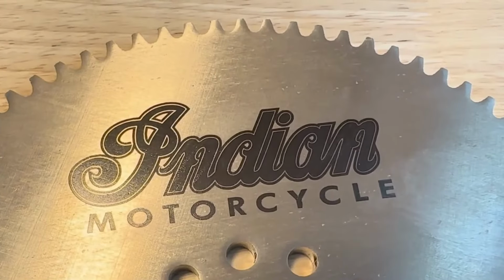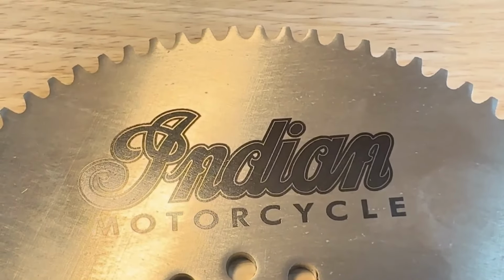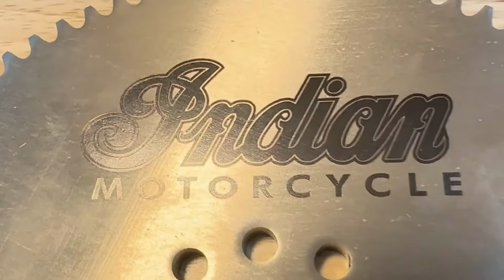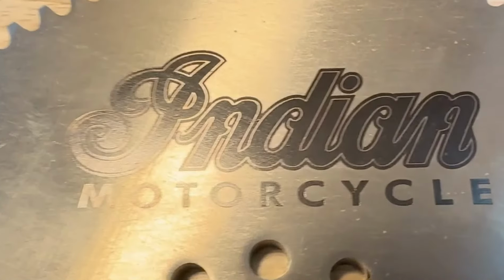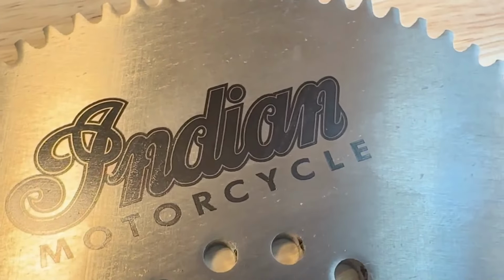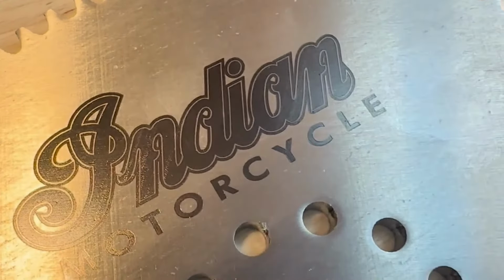Now the third kind of mark we're going to take a look at is an annealed mark. And this is where you're actually getting a color change on top of the metal. What we're doing is we're superheating that metal so that it actually creates oxidization on the metal itself, creating that color differentiation. Now, the result's usually black, but you can also get other colors by adjusting your speed, power, frequency, and focus.